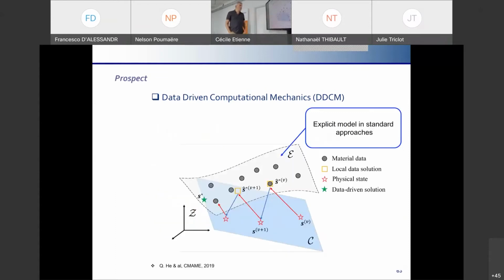data. So, for instance, here, such an approach is based on a subspace in blue, which concerns the physically based part of the virtual twin, and also in gray, the different nodes, which are a couple of nodes. I mean, for instance, stress, strain, quantities from experimental data. Okay, so instead of trying to identify a stress strain law based on a specific theory, we replace such information by the material data, and then we develop iterative processes based on specific Lagrangians in order to reach at convergence a good compromise between a set of partial derivative equations which are physically based and the material data.